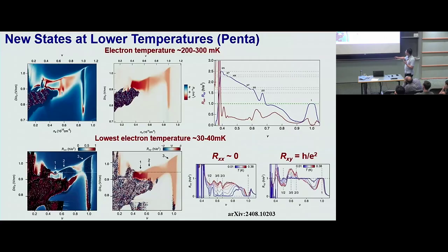But what really grabs your attention is that now there are 3 big patches, okay, 1, 2, 3, that show vanishing Rxx and seem to have uniform colored Rxy, which was not really there, right? So here you have some anomalous Hall, but it's not uniform. And you don't have this little diamond here at half filling. And this region just looks quite different.